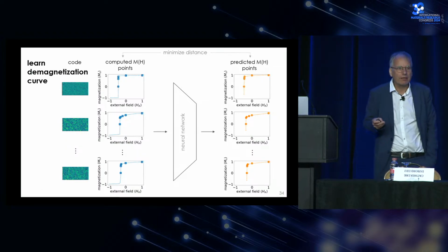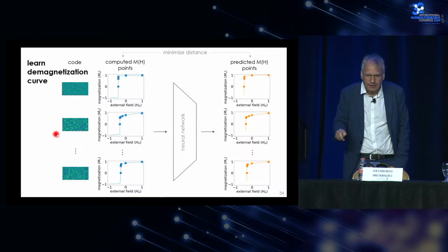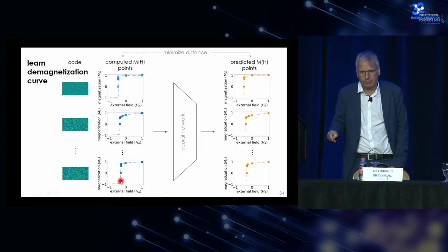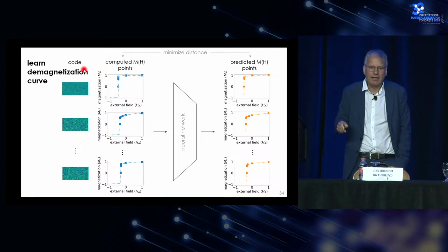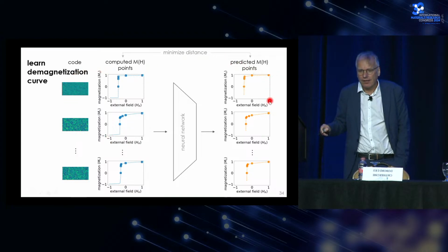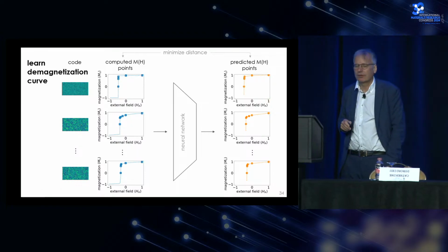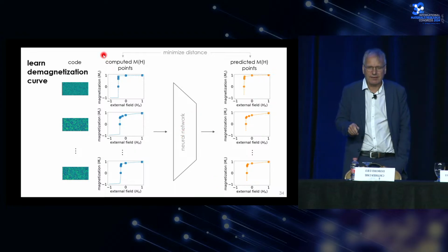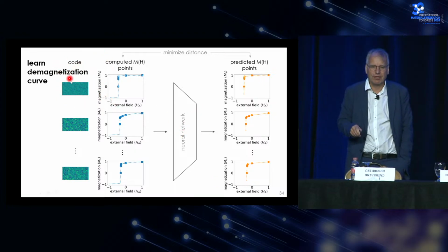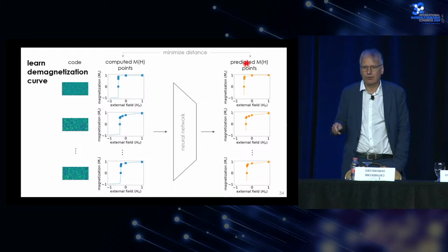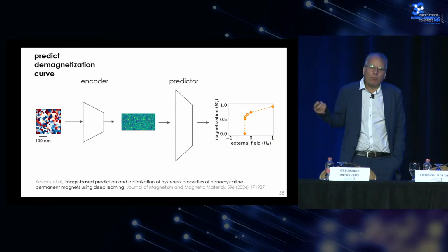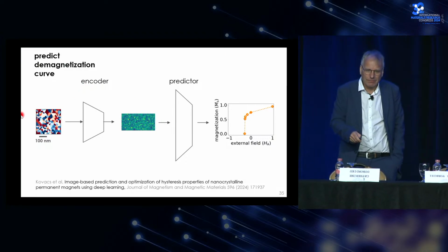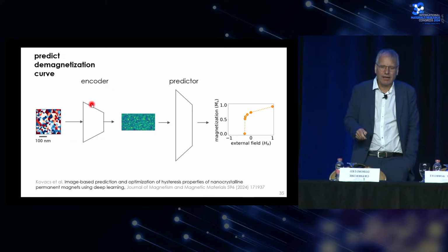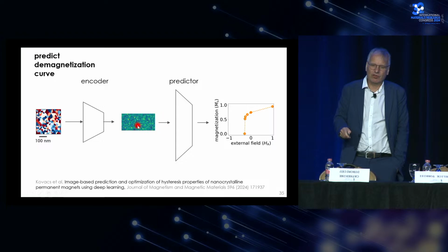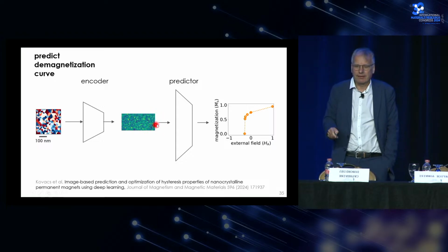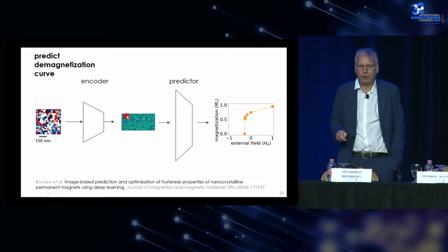Once we have encoded the microstructure of our magnet, we can compute the demagnetization curve because we know the structure, and then we can use the code and learn the demagnetization curve. So we have a neural network that, if we give this code of the granular structure as input, gives us the demagnetization curve. Now we can predict demagnetization curves. So you give me an image of a microstructure, I encode it into a low-dimensional latent code. We have a predictor that predicts the demagnetization curve from the latent code.